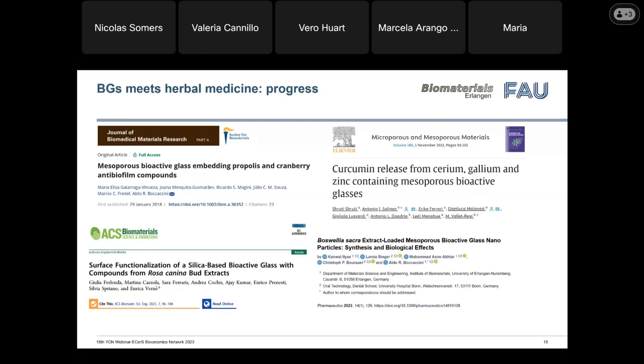And here there is another example of surface modification. This surface modification was done to allow a better loading of the medicinal compound, here Boswellia sacra. They did a quite nice study with BET, showing that when you have this functionalization, the pore size and the surface area of the nanoparticles, because here they use nanoparticles, increased. This allowed a more sustained release of the compound compared to the particles which were not functionalized. Here the authors also showed antibacterial properties, especially against gram-positive bacteria, and they observed a dose-dependent effect.